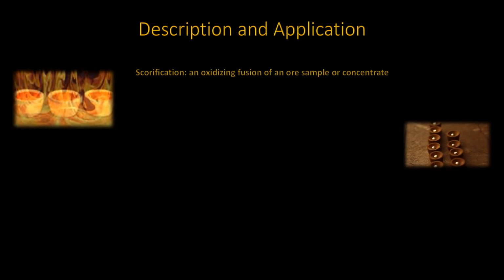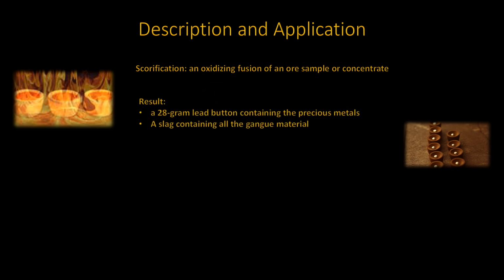Scorification is an oxidizing method for the collection of the precious and noble metals. Oxygen in the atmosphere is used to oxidize the lead into lead oxide, which in turn forms the fluid slag with any silica which may be present in the ore or concentrate. Any remaining lead will form the lead button which would trap the precious and noble metals, specifically any gold or silver. What is achieved is a 28-gram button containing all the precious and noble metals and a slag which contains all that gangue material that is unwanted.